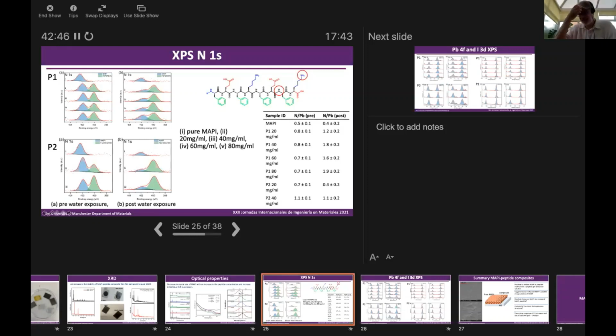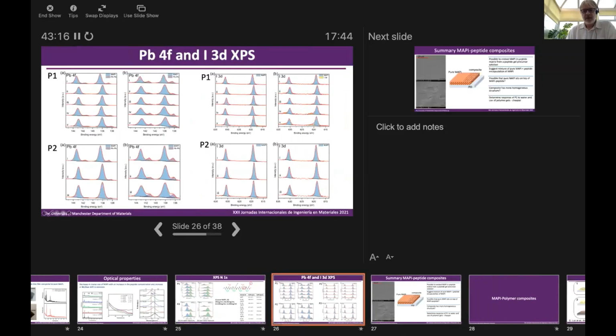This is, as I say, fairly hot off the press, only recorded in the last couple of months. But we find that overall the peptide protected sample with this peptide seems to be fairly stable. With the more hydrophilic system, we actually find the protection isn't that great. Bear in mind, however, that this is only 20 mg per mil for the maximum peptide loading in this particular example.